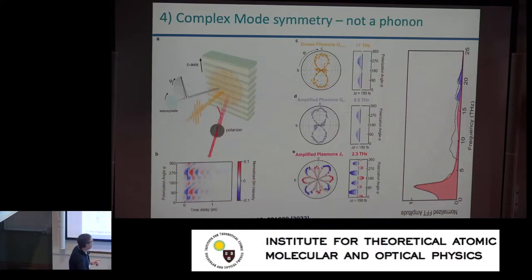And finally, you can look at the flowers as a function of time. This is a little bit of a nonlinear optics trick, but you can convince yourself that this mode is very special. This is not a phonon flower. The B1U phonons that break a mirror twice a cycle look like beans, two beans. Whereas this is some high order, low symmetry mode that is related to this finite frequency. Great. The paper was submitted, rejected in Science, published in PRX, everybody's happy, and so we thought we were making some real progress.